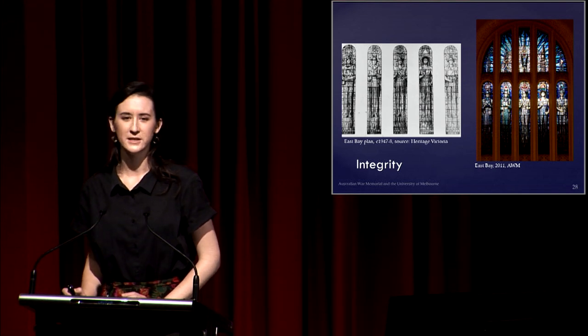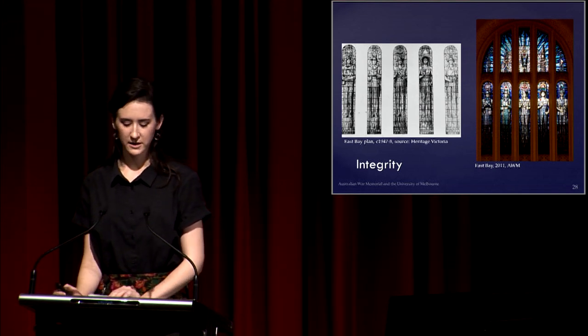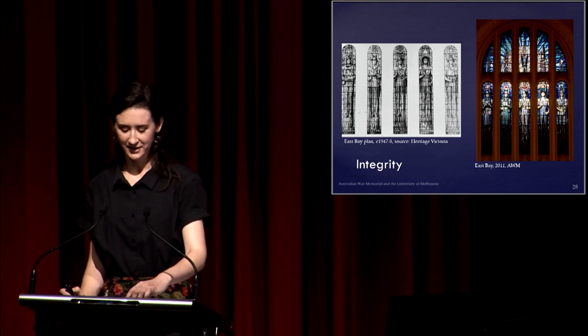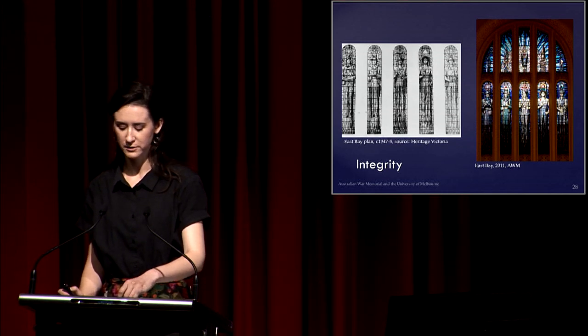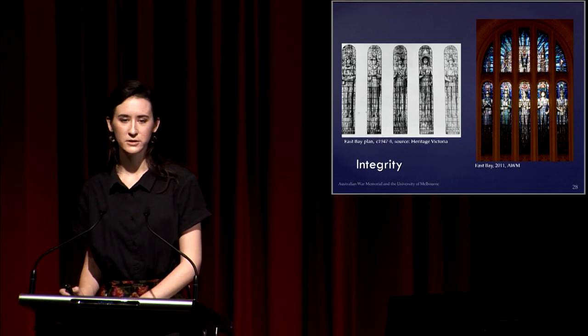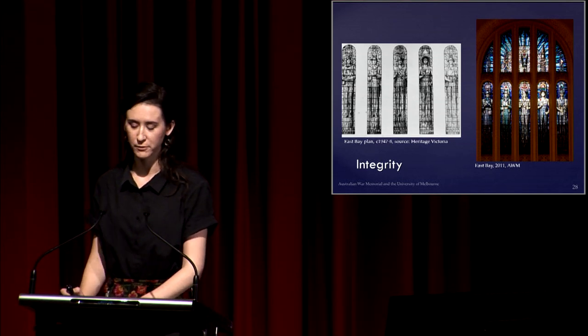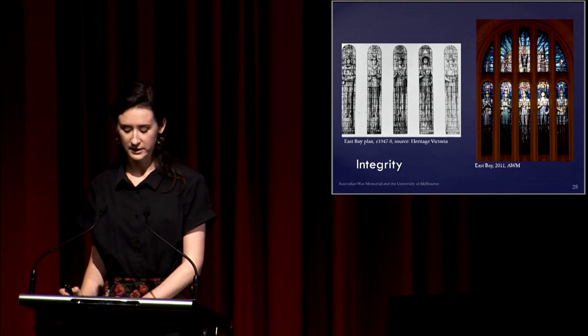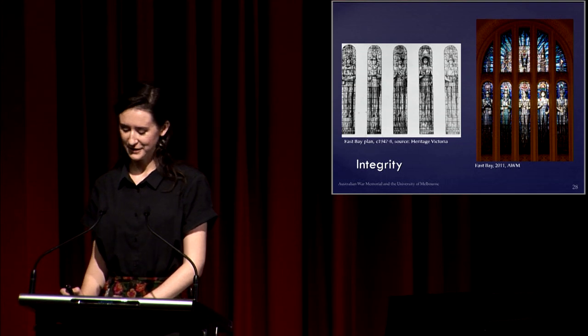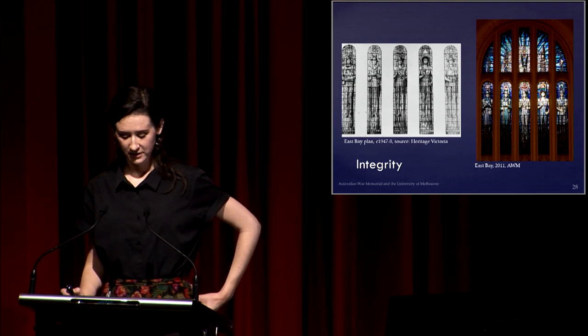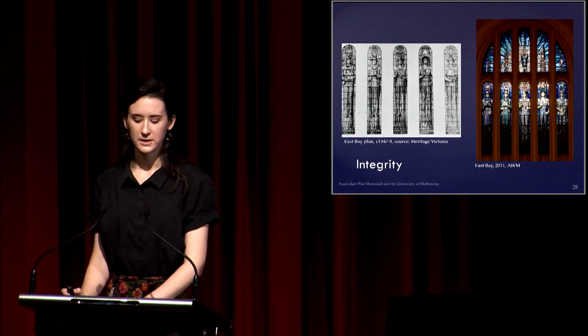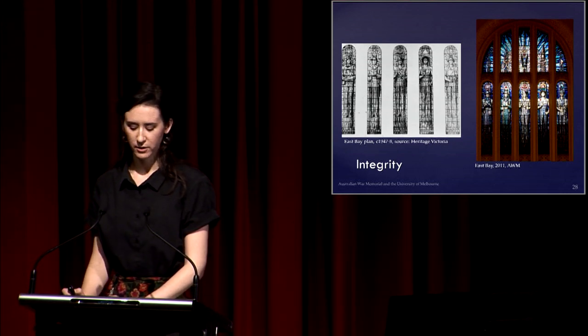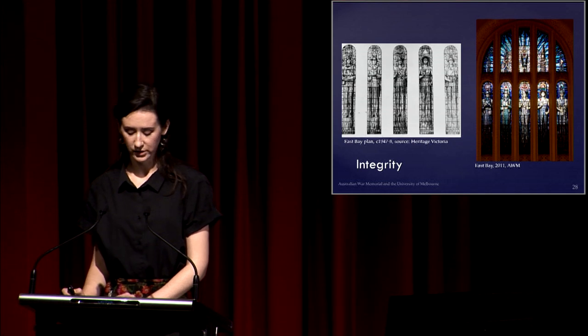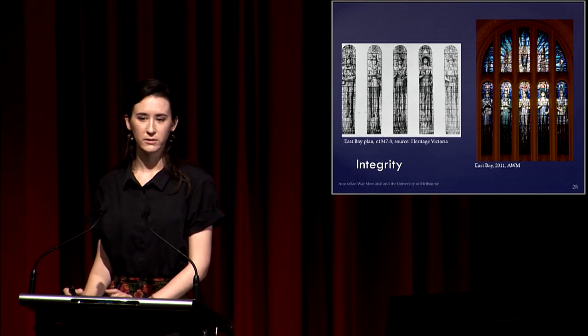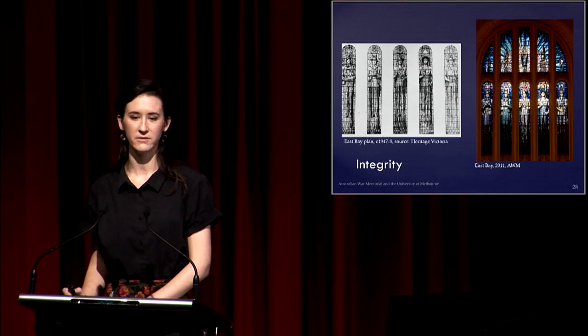So how much of what we see today is original? The answer is, gladly, most of it. There have been some minor repairs and loss of original material, including some minor paint loss due to glass breaks or bubbles in the enamel formed during firing, as well as at least 4 panes, which is out of 9,000, not so bad, of glass that have been replaced due to damage. Several areas of paint loss have also been repainted. However, these are additions, and though some of them are disfiguring, they don't constitute significant damage. All in all, this is insignificant loss over almost 70 years.